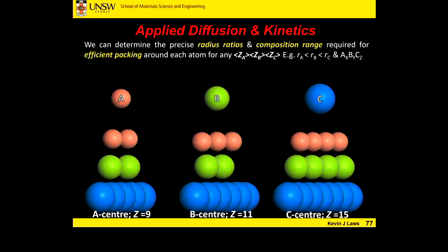So what is this really like in reality in our liquid? Say we have a 3-component system: atom A, atom B, and atom C. Atoms A, B, and C have different sizes. Having different sizes allows us to have a greater number of packing configurations where atoms can touch one another and be jammed in their structure. It's very, very specific. The number of each of these atoms and the radius of each of these atoms becomes very specific to satisfy those conditions, but they can be satisfied.